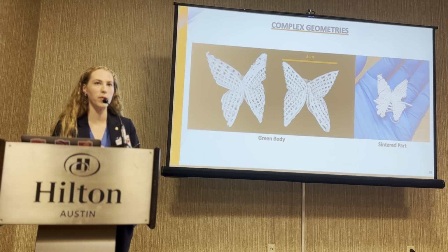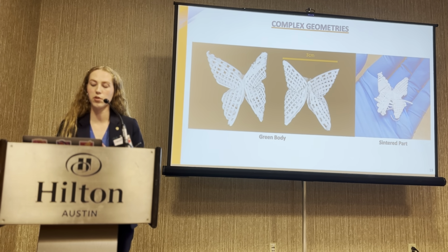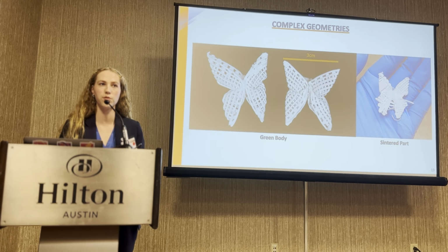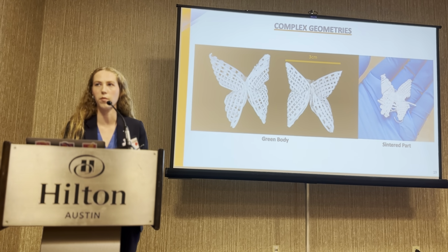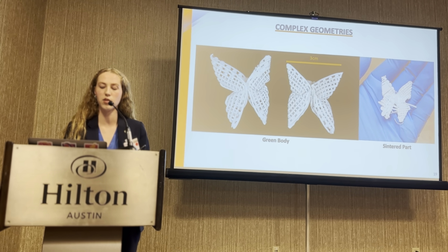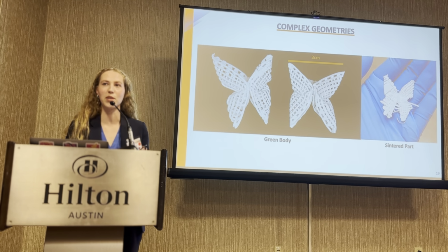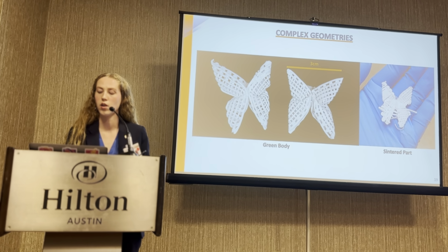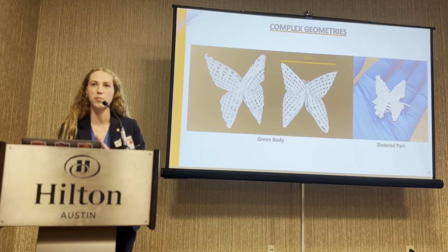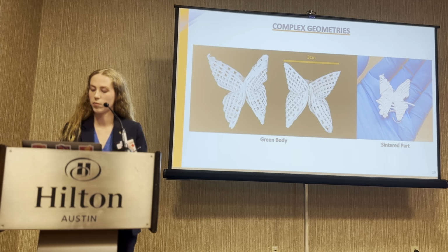One interesting note about this process is that we observed that you need to orient the parts while sintering with the center of mass closest to the bottom of the crucible. So in this case, the butterfly on the right, which was our best surviving butterfly in the sintering process, was oriented on its back, as opposed to putting the wings on the bottom.